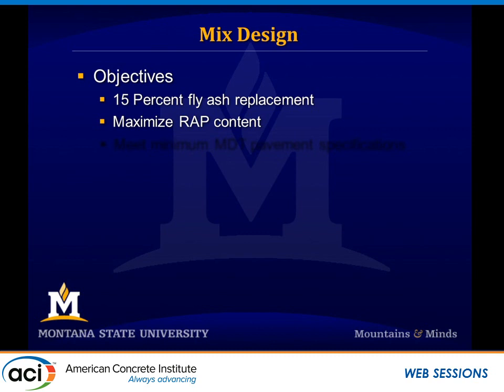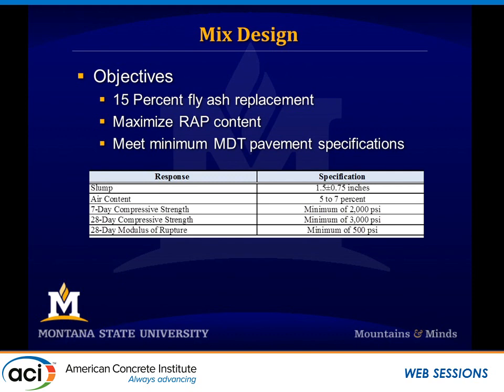We also wanted to maximize the RAP content. Previous research and some of our screening batches told us that you can't replace all the aggregates in concrete, right? If you replace all the aggregates with RAP in concrete, then you don't get a very strong concrete, and you can't meet some specifications. So we had to replace just some of the virgin aggregates with this RAP, but we wanted to use as much RAP as possible. And then we also wanted to meet the minimum MDT pavement specifications, which are a pretty stiff mix of 1.5 inch slump because they use a slip form paver for casting these concrete pavements.